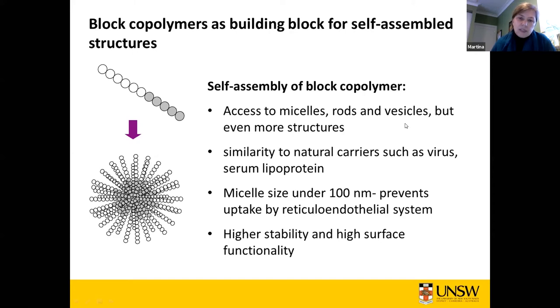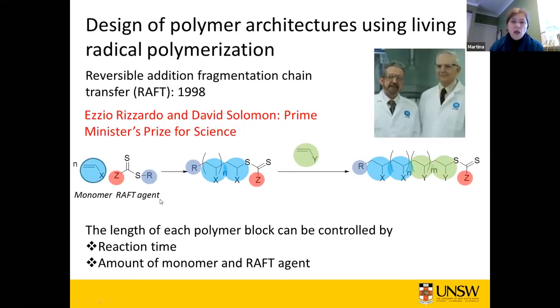And what's nice about them is that they're very similar to natural carriers such as viruses in size. So if we're thinking of micelles, very often they have sizes of around 50 nanometers. That's very similar to your typical spherical viruses. So your coronavirus would have a similar size. So the micelles are also in a good size to prevent uptake by, or the recognition by the immune system. So they tend to circulate a little bit longer, but also we have a lot of surface functionality. So when you look at the end groups here, at every end group, you could, for example, add a ligand.